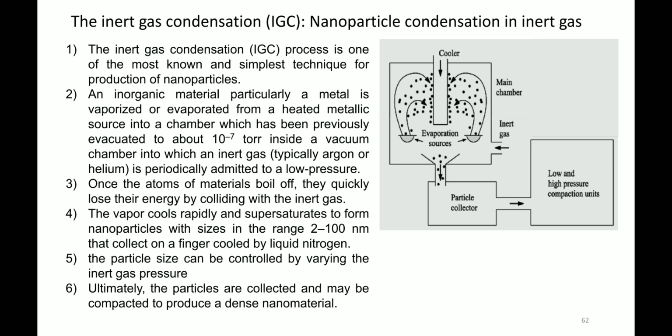The typical particle size is in the range of 2 to 100 nanometer, collected on a finger. As I said, this is called a finger, where you can collect it, and the finger is cooled by liquid nitrogen. So you can see the range of nanoparticles you can prepare is 2 to 100 nanometer, in which we are interested. The particle size can be controlled by varying the inert gas pressure.